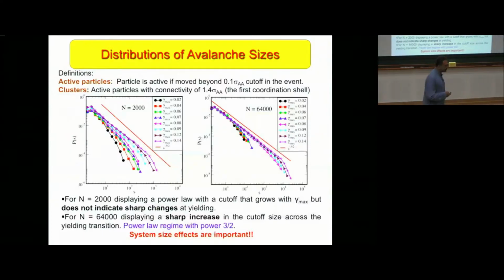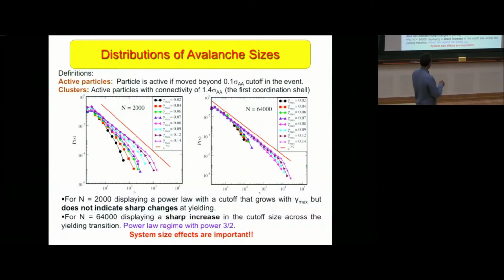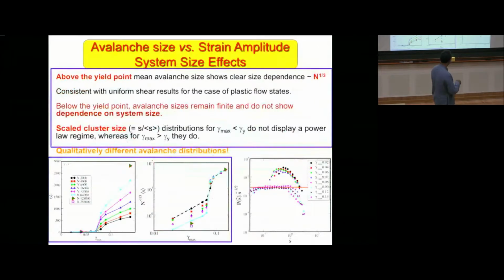In terms of other things that are changing at the yielding transition, one thing I promised was to tell you a little bit about avalanche distributions. The basic observation here, ignore this, is too small. The point is 2,000 particles is too small to tell anything. You have to go to much larger system sizes. And there you see a clear decomposition of the avalanche distributions into finite versus system spanning. So the cutoff here is really determined only by the system size, and you can see that by doing some transformations of variables and multiplying by that power law. And basically, this is now the distribution below yielding, whereas the distribution above yielding is a power law, which would translate in this representation to a flat line, except for the system size cutoff.